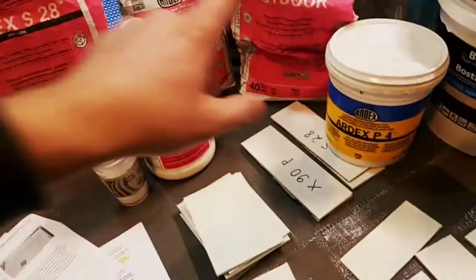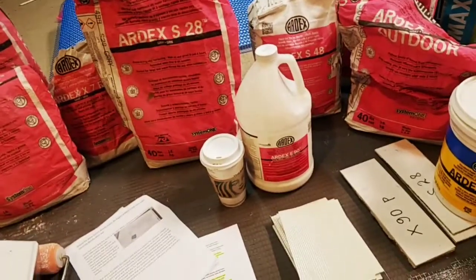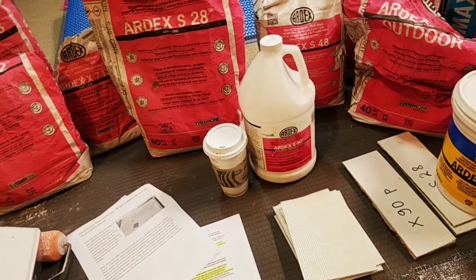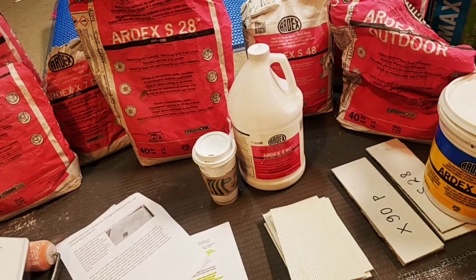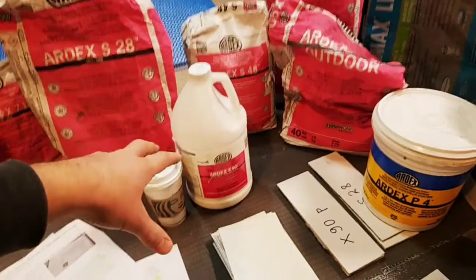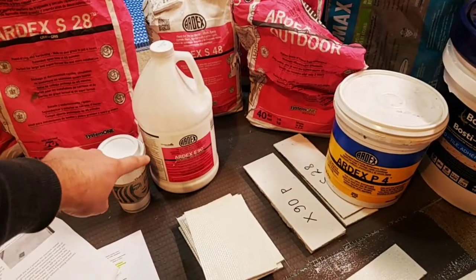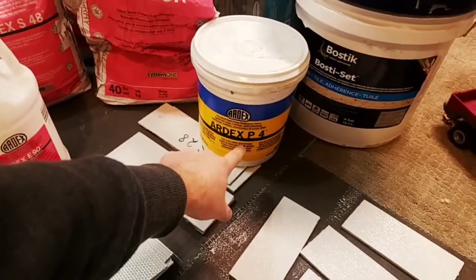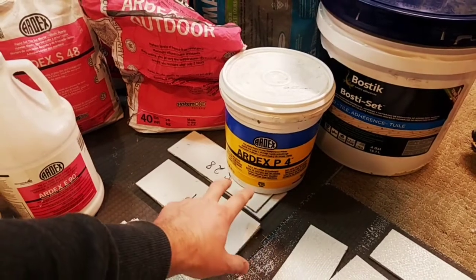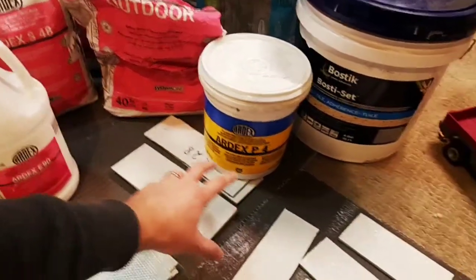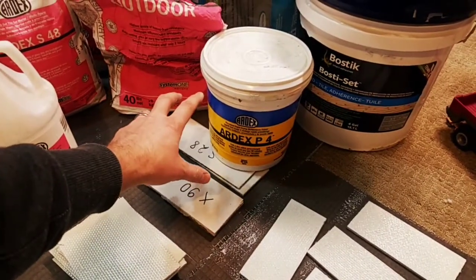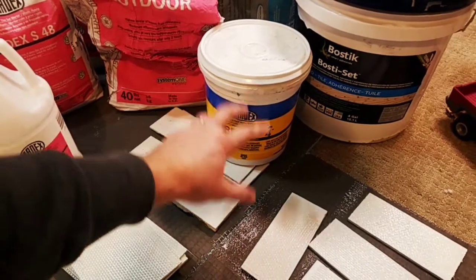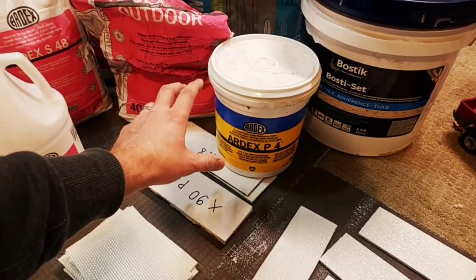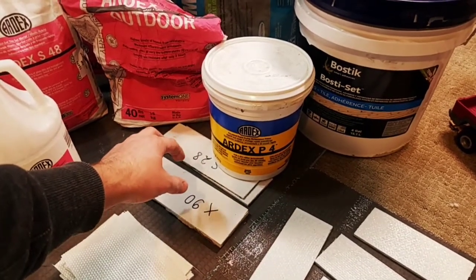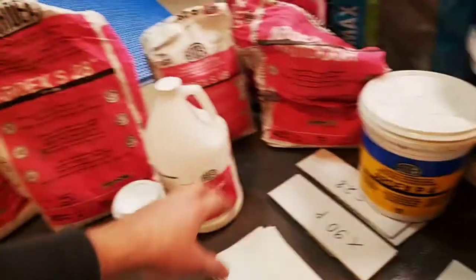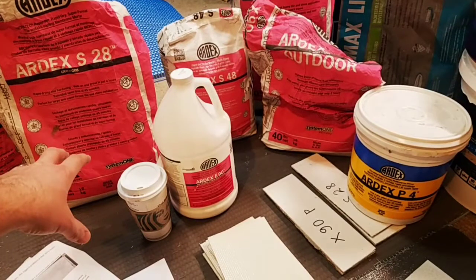About a year ago, we used that product to prime Crema Marfil that was resin-backed. We tested it, and results were just amazing, because we had full bond from the cementitious mortars like Ardex X77 to the back of that stone. I always use this particular product for resin-backed tiles in dry areas. When it comes to installing Carrara marble or light colored marble in wet areas, I'm using a different method, that is an epoxy method, and I describe that method on my website, tileprousa.com, and you can find it on my Facebook page as well.